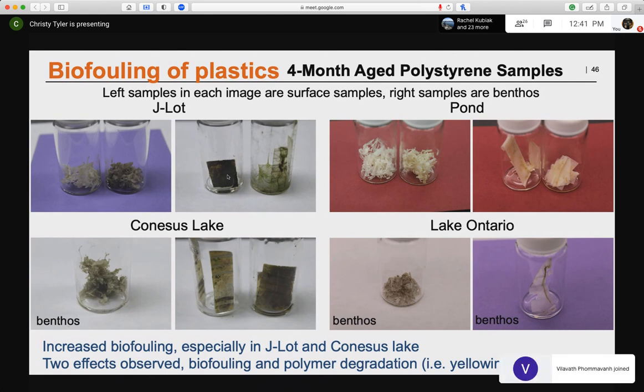If you note in Conesus Lake as well as Lake Ontario, we only have the benthos samples. In some of these, we had some loss of samples. But something to note is that we're seeing more biofouling as we go to longer times. And we're also seeing two different effects occurring. One is this biofouling, this film being formed. We're also seeing the biodegradation.